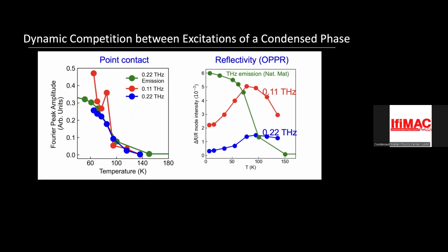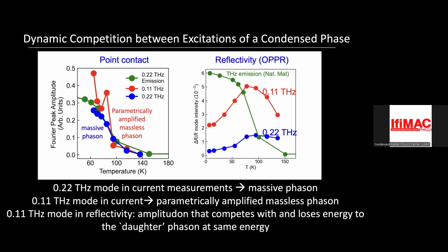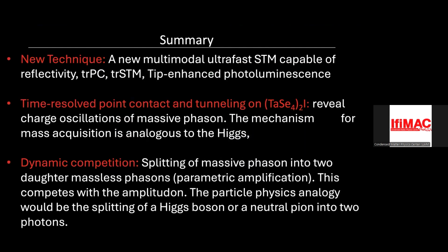So this is the data that we have. We have the point contact and STM showing the existence of two modes, one at 0.22, which we believe is the massive phason, the other at 0.11, which is a parametrically amplified massless phason. That massless phason competes with the amplitudon, which we see in our reflectivity measurements. So that's the story.